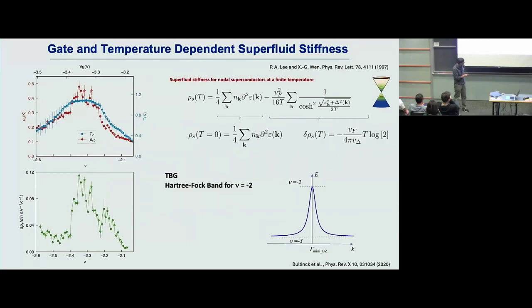Just looking at this band structure I can plug in there, I can more or less explain this behavior, right? Because you can see that here it is hole-like turning into electron-like, and that mass becomes kind of infinite at some point. When mass becomes infinite, it vanishes, and from there on the carrier sign changes. Therefore, Nk here, that Nk drops. This is explained by, again, just looking at the zero temperature behavior, which is just the dispersion relation of the band, right?